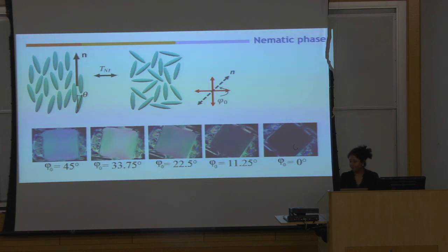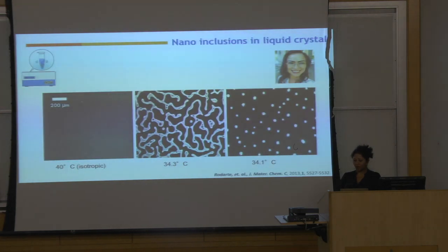Do you have any control on the thickness of the shell? That's a good question. We have some control over the size of the shell based on how quickly we do this cooling. So we go from isotropic to nematic. It's the same temperature change over which we cool it down when we are doing the shell formation. If we cool very fast, if we quench the system, the shells are smaller and the diameters are thinner. So there is a correlation, but as of now, we have not been able to form a case where we can hold one and just change the other. So they both change at the same time. And if we go slower, we can make bigger shells.